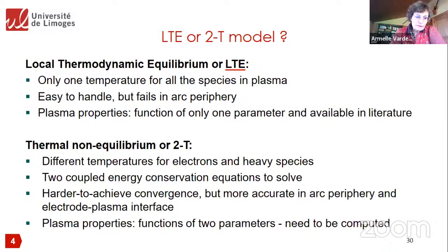But one of the major problems with this model, if you want to use it for plasma forming gas mixtures with hydrogen and argon, for example, nitrogen and hydrogen, or helium and argon, is that you will not find the properties of the gas in the literature, and you have to compute them.